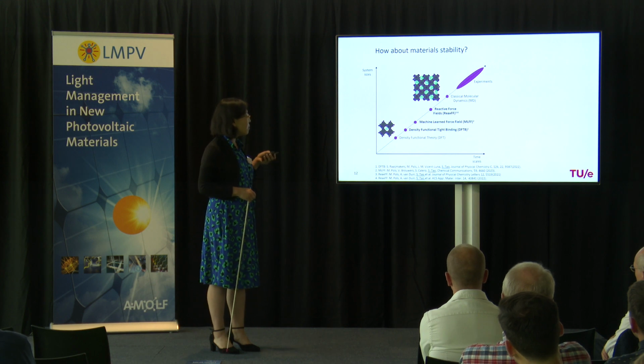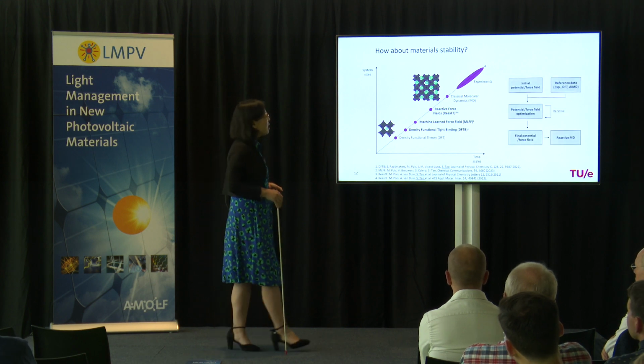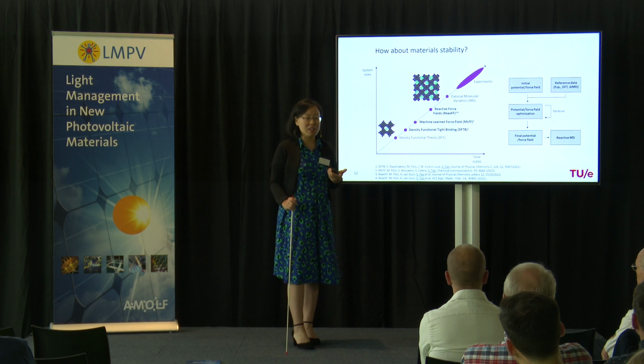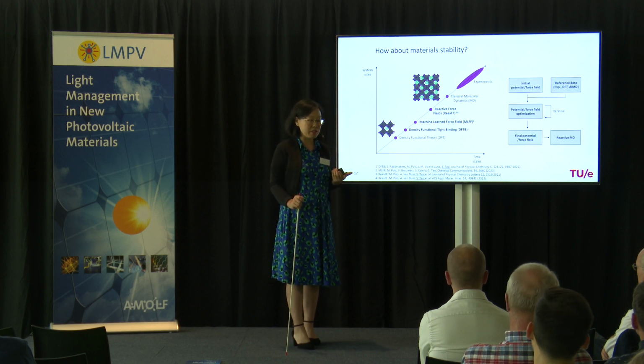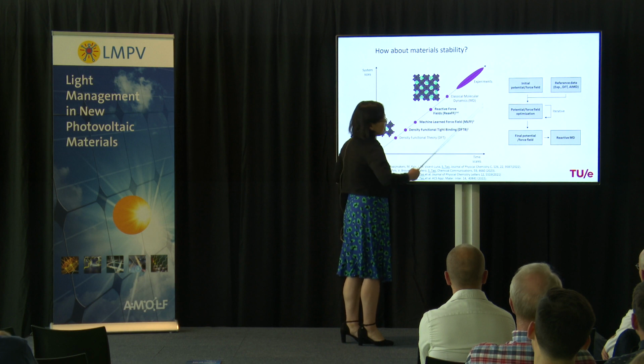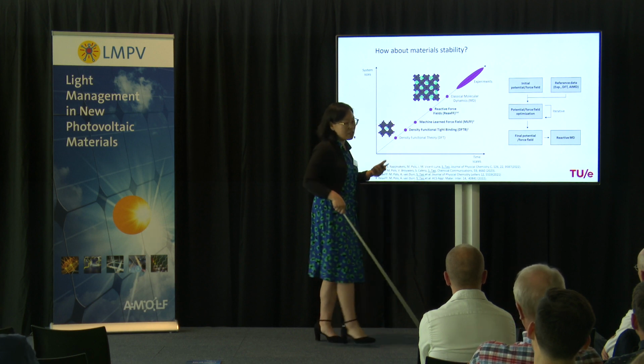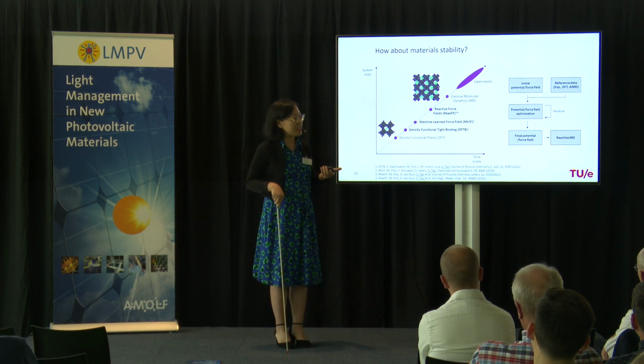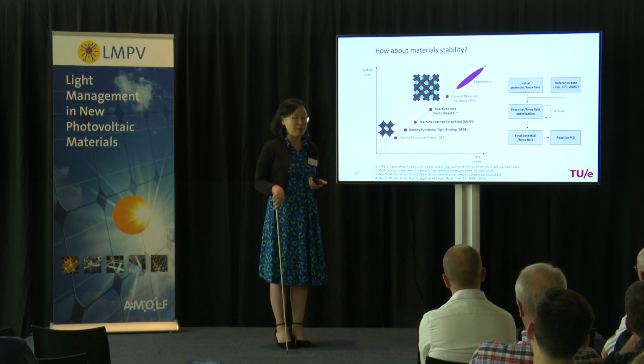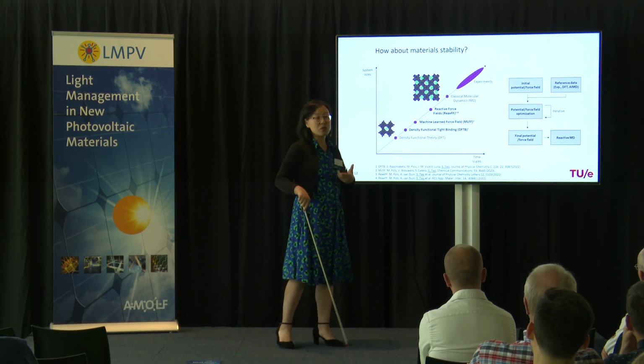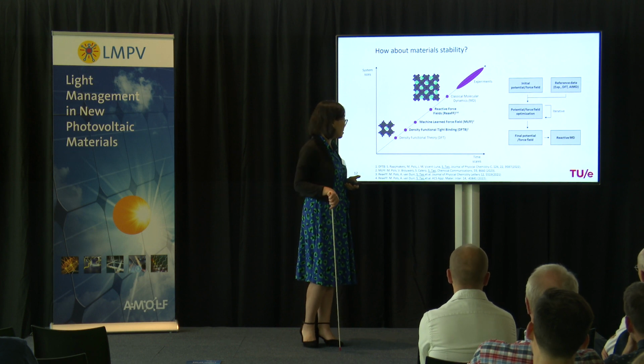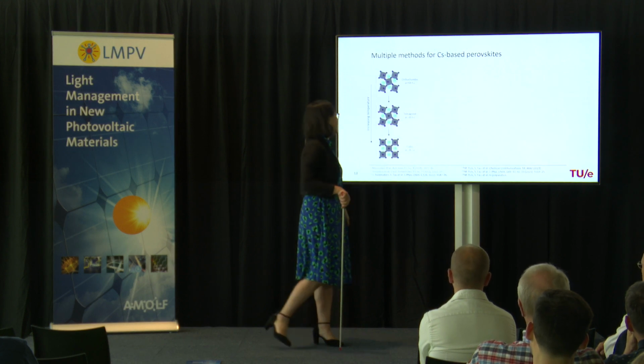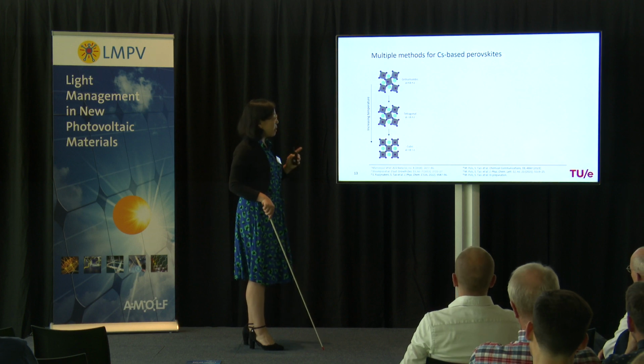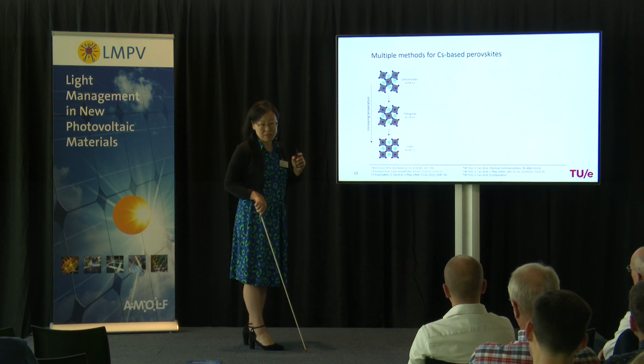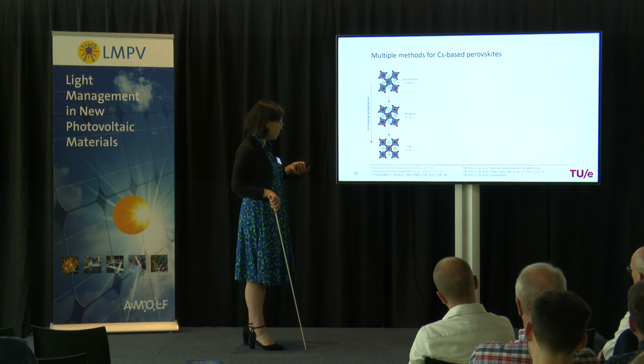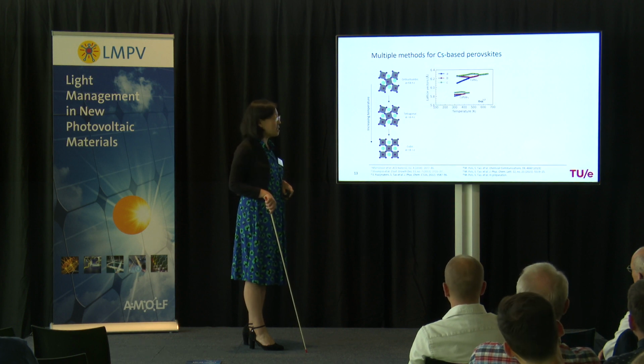The philosophy of developing this method is basically we start with either very accurate quantum calculation data or experimental data. We do iterative training until our force field, our potential, produces accurate DFT or experiments. And then we use that to do large-scale molecular dynamics simulations. One of the characteristic properties of perovskites is phase transition as a function of temperature, so we take advantage of this property to validate our models.